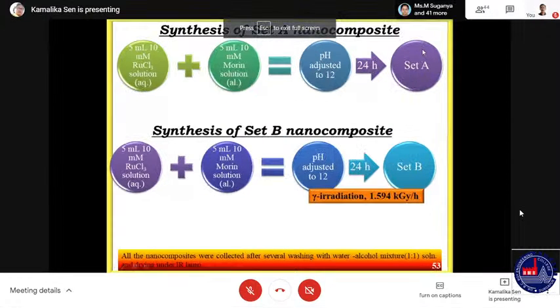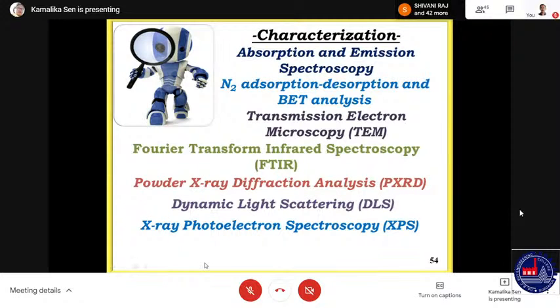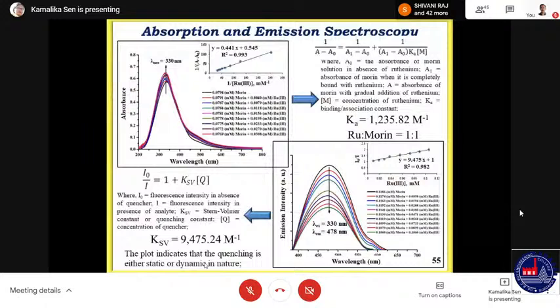This is our set A, which we call non-irradiated sample. Similarly, we have taken the solutions just like the previous ones and irradiated it for 24 hours in the gamma chamber. Now the dose rate in the gamma chamber was only 1.59 kilogray per hour, and all the nanocomposites were collected after several washing with water alcohol mixture and dried under an IR lamp. Then we characterized it, and yeah, this is the characterization.